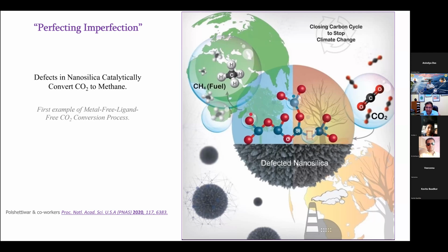Silica is SiO2, a simple amorphous random network of silicon and oxygen, so we call it siloxane. The question we asked is, what if I break these Si-O bonds? Then I get an Si radical and an oxygen radical. Can they activate CO2? Can they dissociate hydrogen? What if I break both Si-O-Si bonds? Then I get an oxygen vacancy. See here, it's Si, no oxygen is missing, then Si.